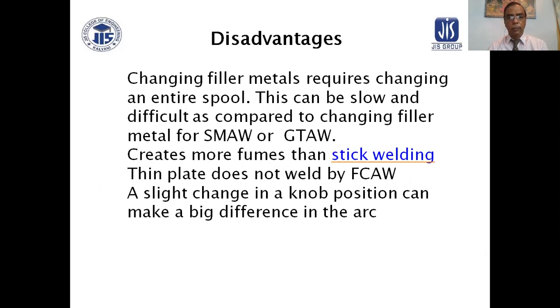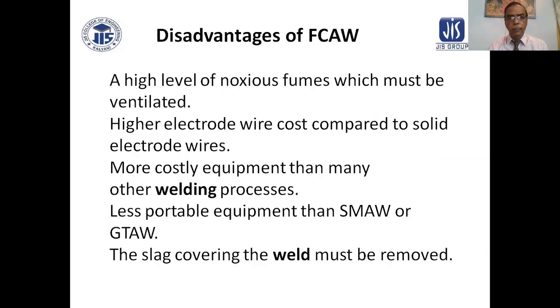Disadvantages: changing filler metals requires changing the entire spool. This can be slow and difficult as compared to changing filler metals for shielded metal arc welding or gas tungsten arc welding. Creates more fumes than stick welding. Thin plate does not weld well by flux core arc welding. A slight change in a knob position can make a big difference in the arc. A high level of noxious fumes which must be ventilated, higher electrode wire cost compared to solid electrode wire, more costly equipment than many other welding processes, and less portable equipment than SMAW or gas tungsten arc welding. The slag covering the weld must be removed.